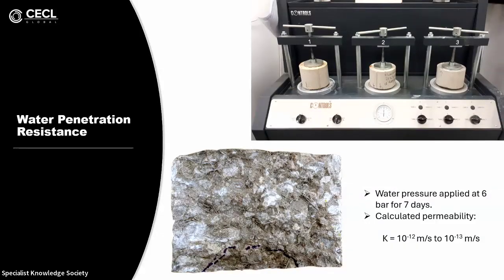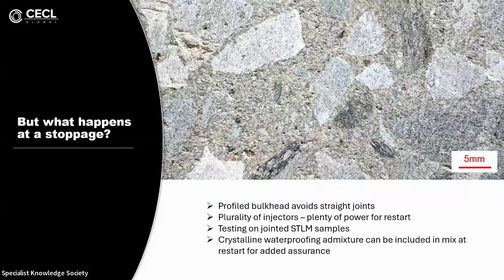Looking at water penetration testing, we've done water penetration testing on samples to give an estimate of permeability. Owing to the high density and low porosity of the material, the calculated permeability from the water penetration test is very low.